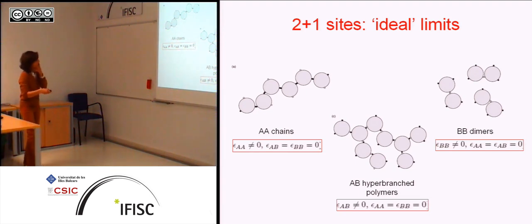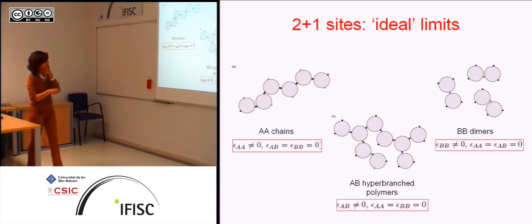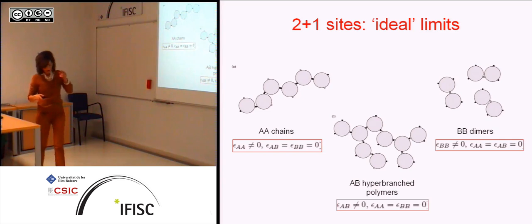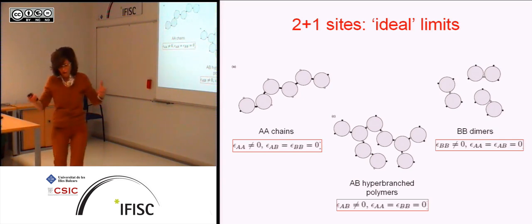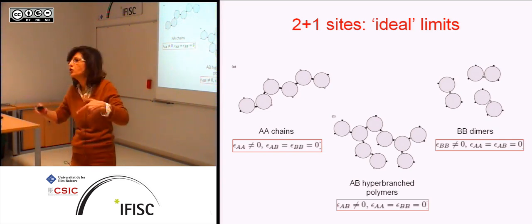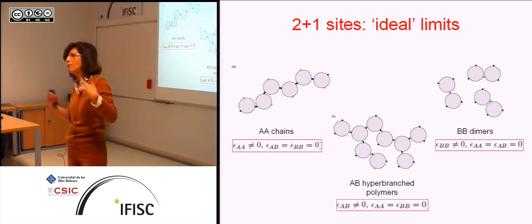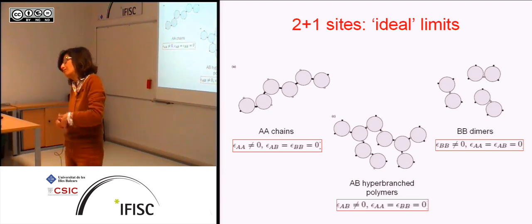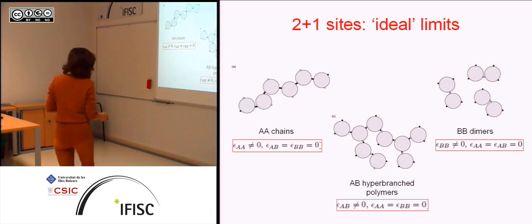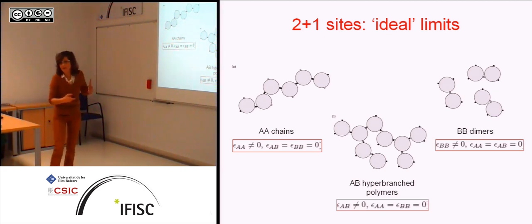And this is the hyperbranch limit. This is the same system, but now you switch off the like interactions. You only allow the A's to interact with B's. What we form are polymers that are the most branched. That's why they call them hyperbranched polymers. You only have one bonding probability between unlike sites, and these are hyperbranched polymers. All these three limits are ideal, so we know what we're doing.